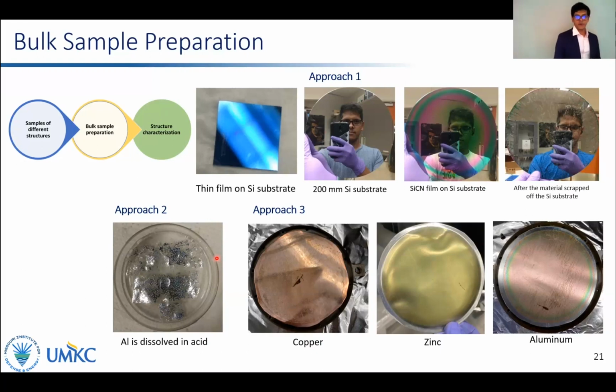So we deposited films on different metallic substrates such as copper, zinc, and aluminum, which have contrasting thermal expansion coefficients compared to silicon carbide. After depositing these films, we vacuum sealed them and cooled them in liquid nitrogen. Because of the thermal expansion differences, the films peeled off the substrate and we could collect powder samples.